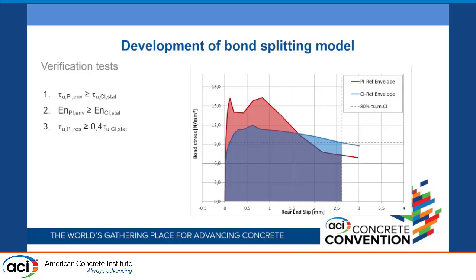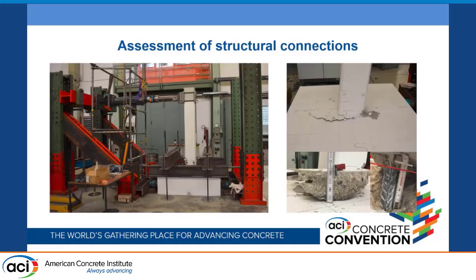than that of cast-in, the energy dissipated by post-installed should be more than the energy dissipated by cast-in, and also the residual capacity should be more than 40% of the peak load of the cast-in. So that way we first developed the bond splitting model, and then we wanted to see how we can apply that to the structural connection.